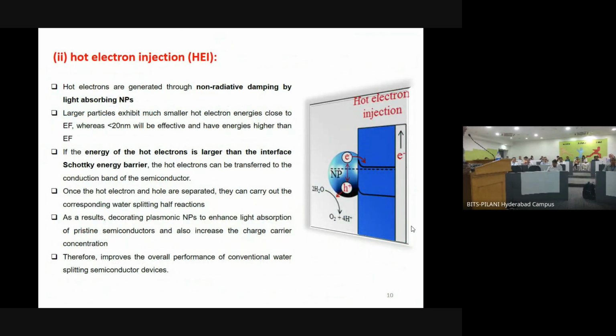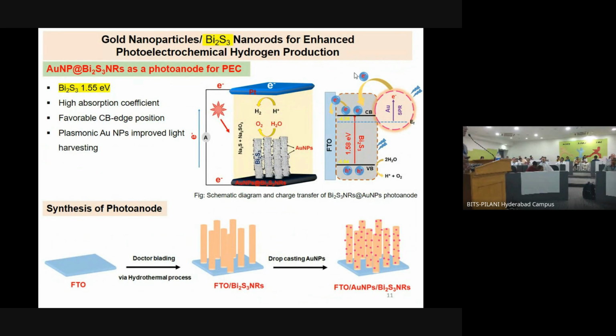The additional effect which you can think of is the hot electron injection, because as I said, there is a barrier which is inbuilt. When you put a metallic object on a semiconductor, there is a barrier, otherwise the electron flow cannot happen. So for that, you need to have some kind of small particle which is highly energetic. If the particle is so small, it has a possibility, especially for this. In the case of gold, I think you need to have a size of at least less than 20 nanometers.